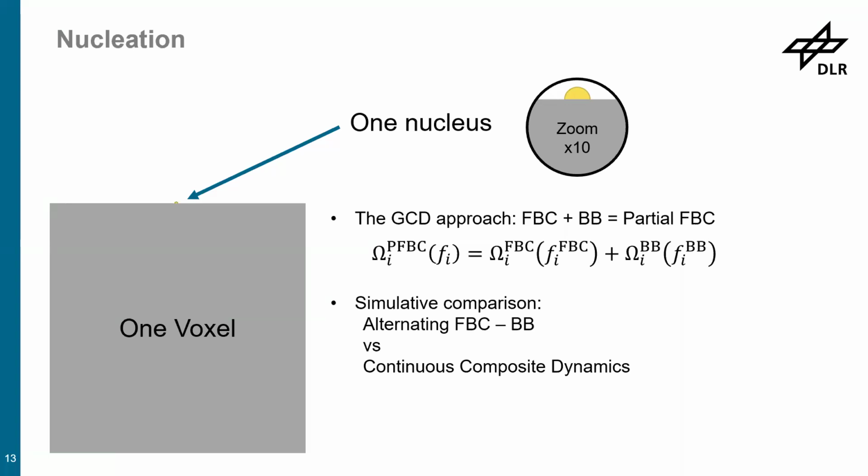And there are some approaches where they say, yes, we assume it's 50 or like 25% reactive till it covers everything, and then they convert it to a fully reactive part. But it also has only one step in between. Whereas with this, it's continuous. I can calculate what the precipitation rate is, what the coverage is, and from there, the composite fraction.